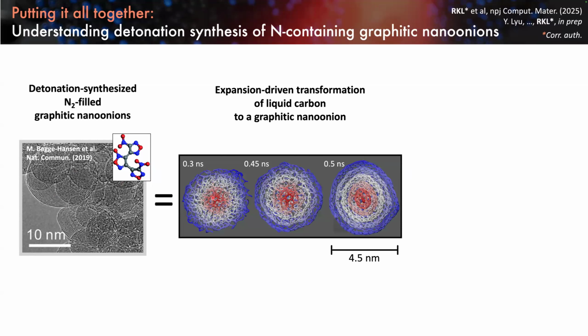Each one of these particles is at a different time point along that quenching pathway. They're colored by radial position - red means you're in the center of the particle, blue means you're at the surface. What you see, for example, at this 0.45 nanosecond snapshot is that you're forming these layers of this graphitic nanoonion, and you're doing this from the outside in. That's something interesting we're going to remember for a moment.